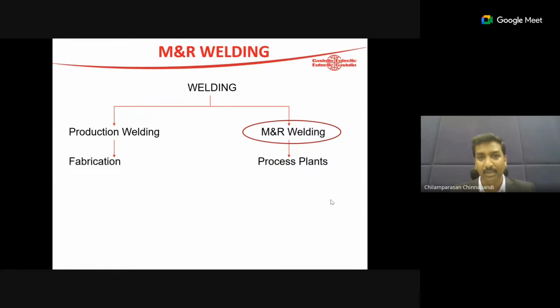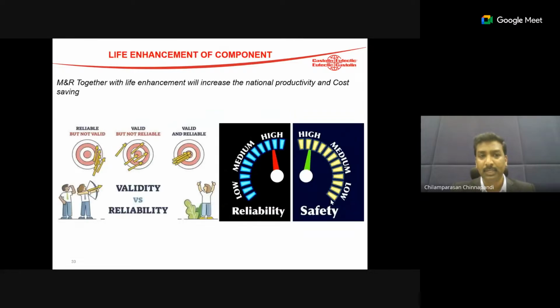For example, cast iron will have almost 15 to 20 different electrodes being used, because over a period of time the product in service becomes fatigued, and it has stress induced, heat affected zones, and many other problems. So a normal electrode will not work again. We have high alloyed electrode products which can give you better strength and low heat input to the base material, so that it can be brought back to the original shape. At the same time, the life will be enhanced.